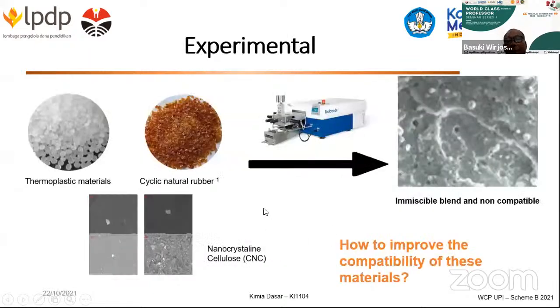This is the simple thing actually. When we blend thermoplastic polypropylene especially with cyclic natural rubber, cyclic natural rubber is not like rubber. It is actually thermoplastic, because it is not elastic anymore, as it has been cyclicized. The cyclic degree is about 70%, so only maybe 20-30% of uncyclicized rubber is left.